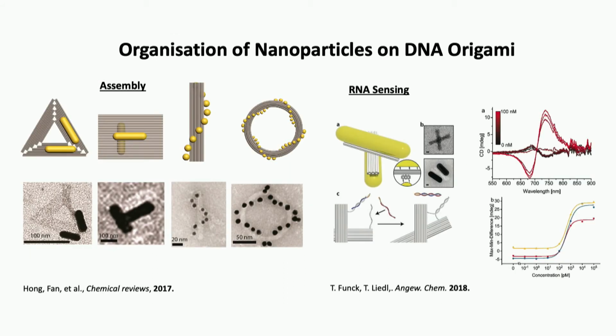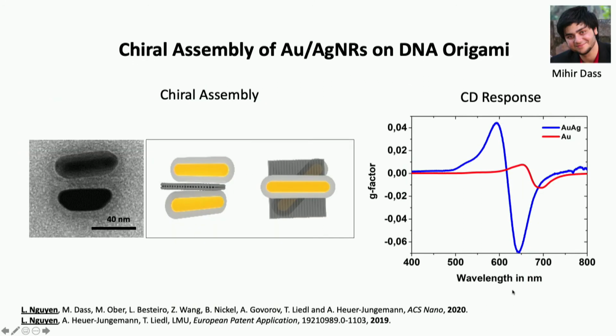Controlled assembly of nanoparticles on DNA origami has been done for a long time. You can make chiral structures, structures that can sense RNA in blood, for example, such as these nanorod structures here that came from our group as well. And we did a chiral assembly as well, and we could show, as you can see here, that the chiroptical response from these core shell nanorod assemblies is much, much stronger compared to the pure gold. So this basically means we could, in theory, use them, for example, like the RNA sensor in the switch beforehand, for very sensitive detection of RNA.